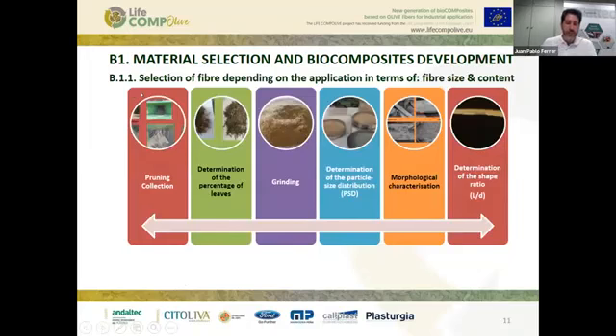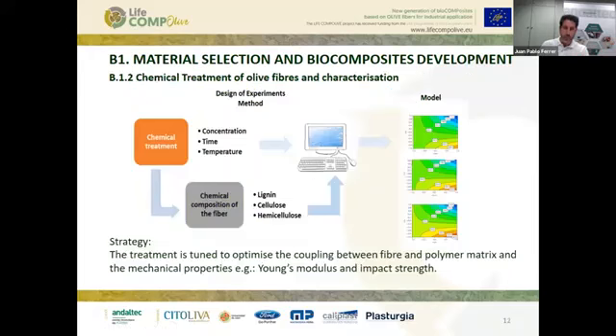So in the first sub-action, we began with the pruning collection. We characterized the pruning, we determined the percentage of leaves in the pruning. We did the grinding of that biomass, and we also characterized the composition and the particle distribution of the fiber. We performed also a morphological characterization by electron microscopy, and we also determined the typical aspect ratio or shape ratio of the fibers.